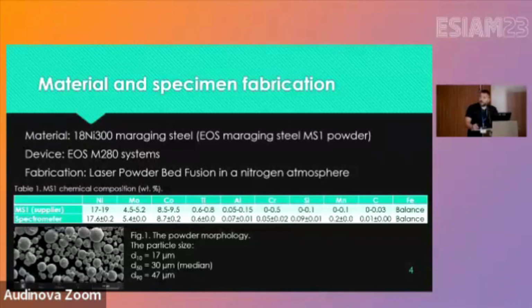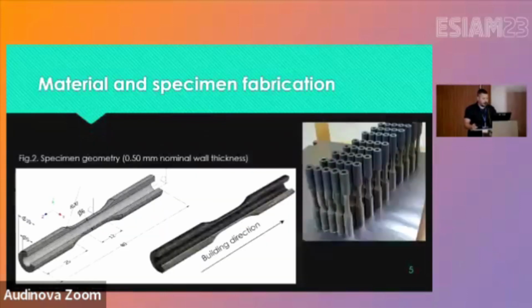So a few words about the material. Like I said, EOS Maraging MS1 powder. It's the 18Ni 300 Maraging steel. We used the same printer as before, an M280 from EOS. Here's the material composition from the supplier and from our own test with the spectrometer. They're quite the same within a range. Also, the particle size of the powder was tested, and the median was about 30 micrometers, with 90% of them below 47. So, yeah, I would say standard.